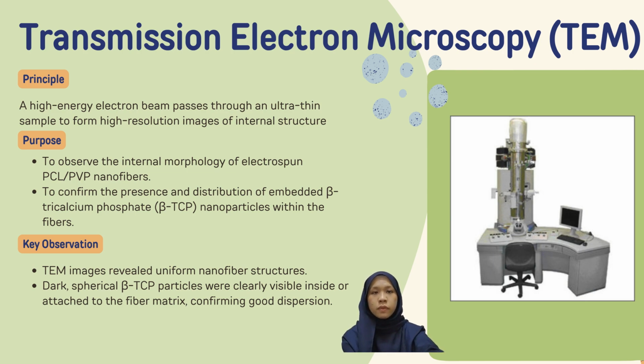The key observation for TEM is TEM images reveal uniform nanofiber structures. Dark spherical beta TCP particles were clearly visible inside or attached to the fiber matrix, confirming good dispersion. The advantage of TEM is very high spatial resolution, about 1 to 2 nanometers, enabling visualization of nanoparticle-fiber interaction. The limitation of TEM is that it requires complex and ultra-thin sample preparation. And lastly, the equipment is costly and requires skilled operation. These are examples of TEM images.